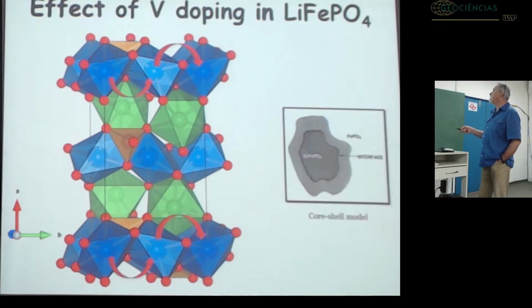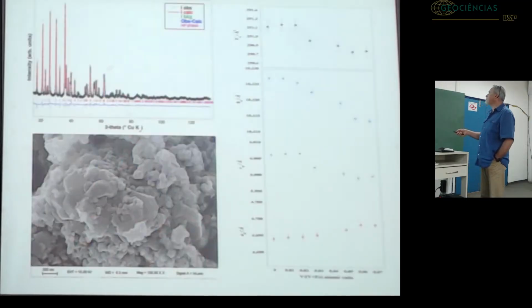And basically, the lithium diffuses from one octahedron to the other, and can exit the grains of lithium iron phosphate, creating regions of FePO4, which is heterosite, mineralogically, olivine structure, with trivalent iron in the M2 and M1 vacant. And basically the heterosite grows at the expense of the triphylite during charge. The reverse happens during discharge.